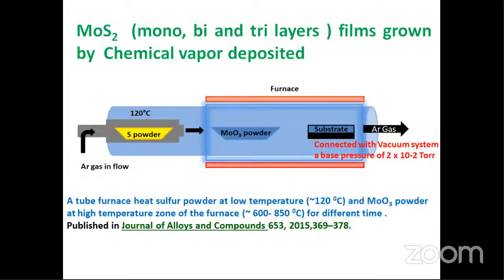For this CVD method, we have used a two-zone furnace: one is the lower zone, and the other is the higher zone. In the lower zone, we are putting our sulfur powder. Sulfur's melting point is very low, nearly 120 degrees centigrade, and in the other zone is the MoO3 powder. MoO3's melting point is very high, but we have basically used a vacuum system. This is a vacuum of nearly 10⁻² Torr, and near this MoO3 powder we are putting our silicon oxide substrate, and the whole reaction takes place at different temperatures and different times.